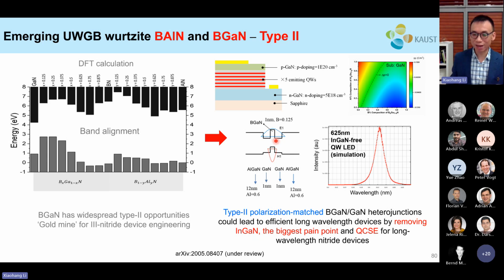And because of this type 2 heterojunction, although BGaN and GaN are larger bandgap materials, we can essentially push down the optical transition energy in this quantum well to about 2 electron volts or so. So that will generate, again from the simulation, about 625 nanometer. And this quantum well combination also realizes polarization matching. I will talk about polarization later, but it can reduce or mitigate the quantum confined Stark effect, which is a major issue in high indium quantum wells too. So this is quite interesting, and hopefully we can do more experiments to verify this.